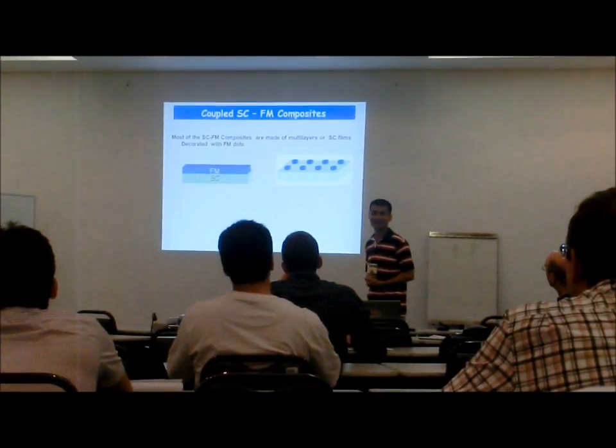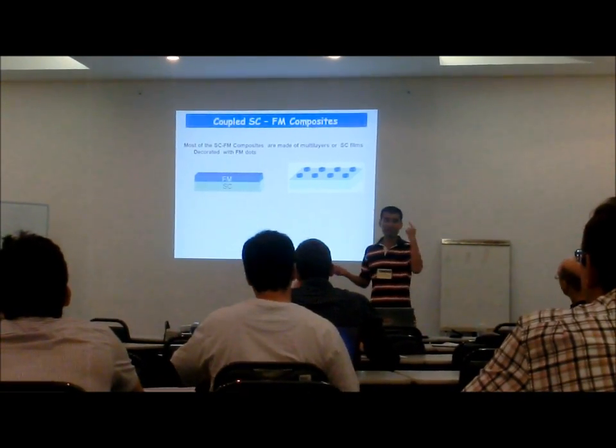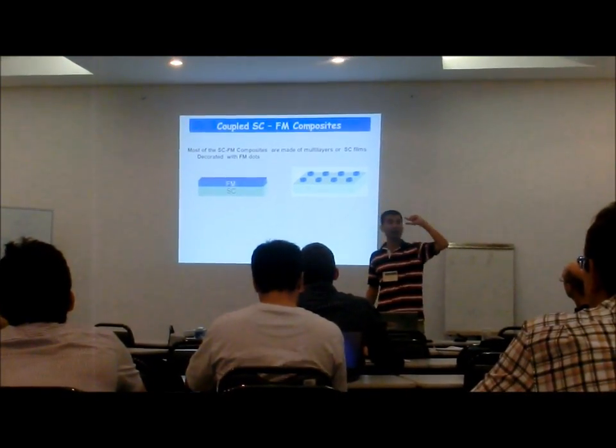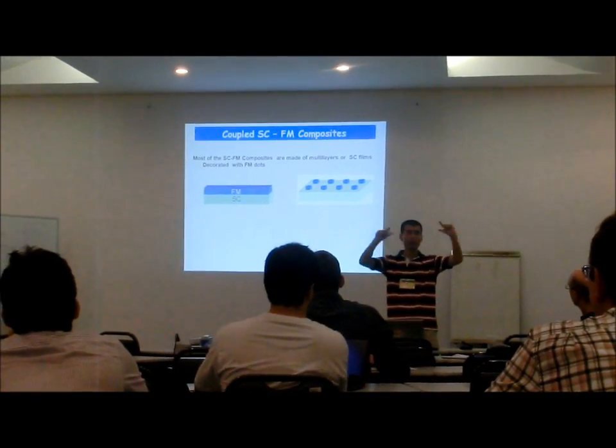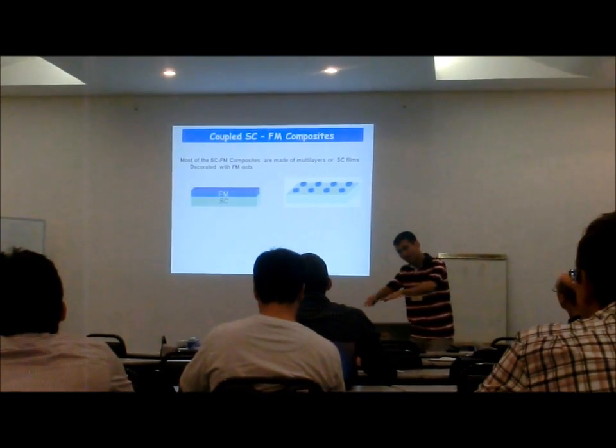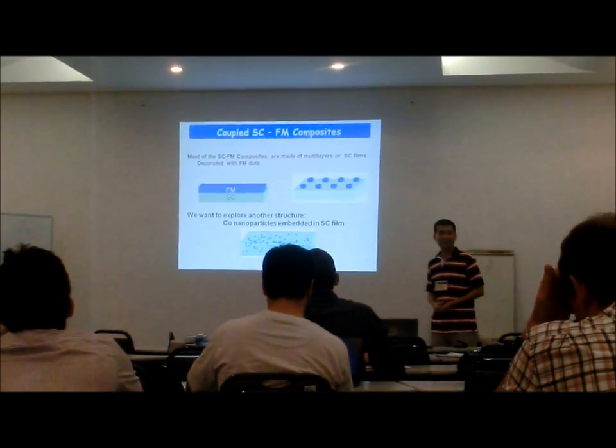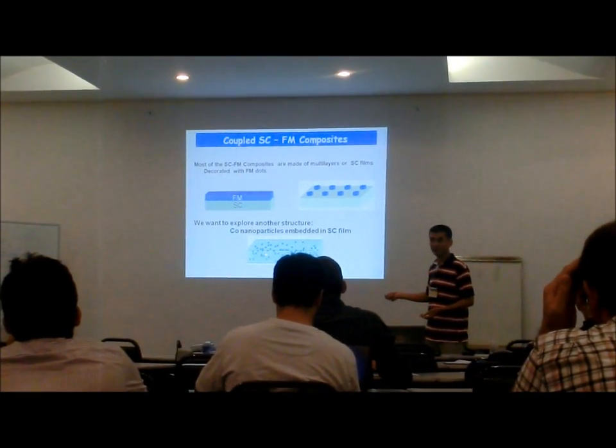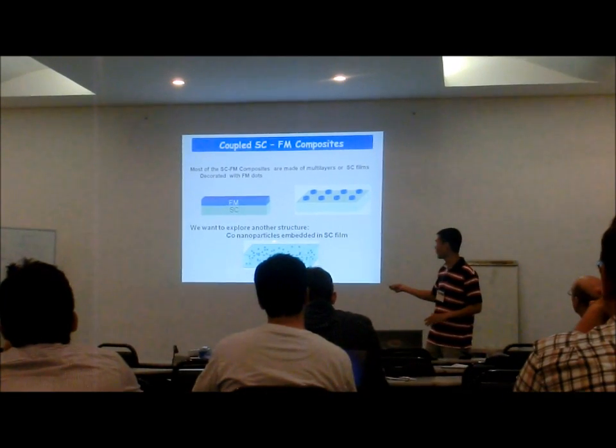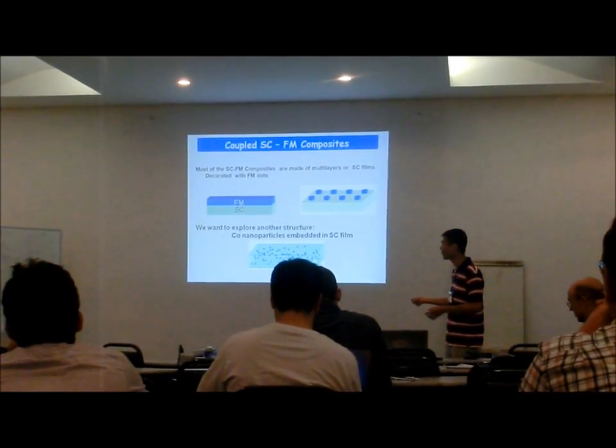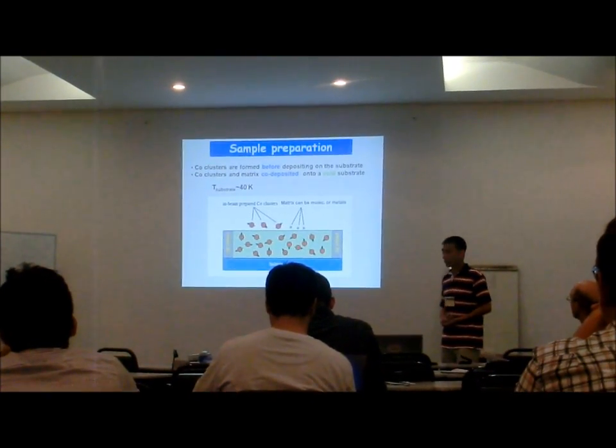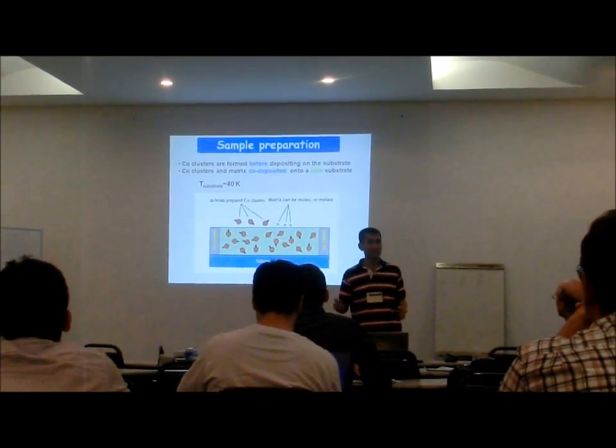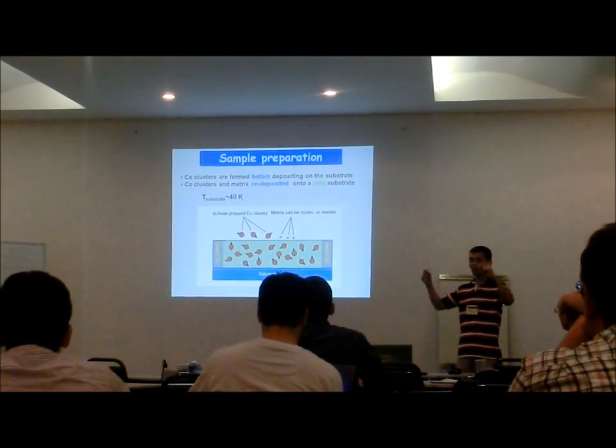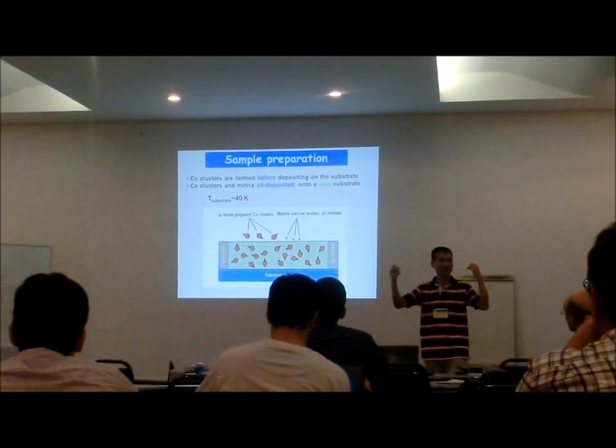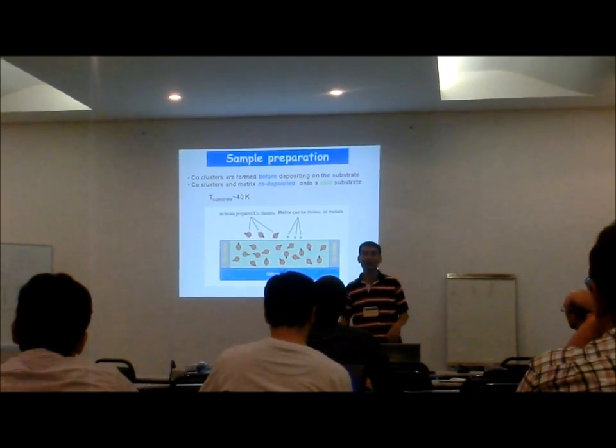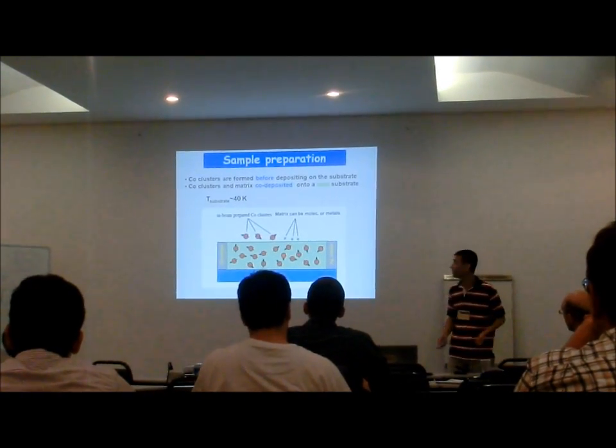Then I checked the literature. Then I found out that most of the books are focused on the bilayers or multi-layers or superconducting thin films with ferromagnetic layers on top or below. So it's very nice for us to study this kind of properties because few work has been done for such system. So we decided to do such a study. The preparation is very easy to say, very difficult to do. We just codeposit cobalt nanoparticles and lead on a very cold substrate. Here we use sapphire.